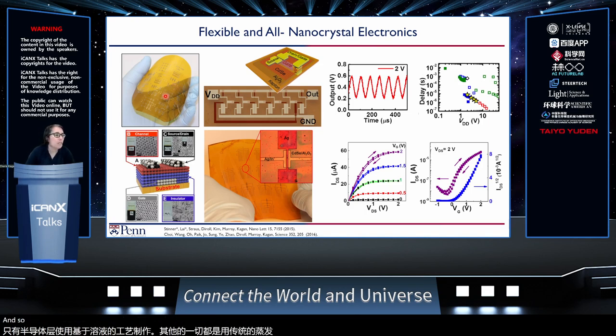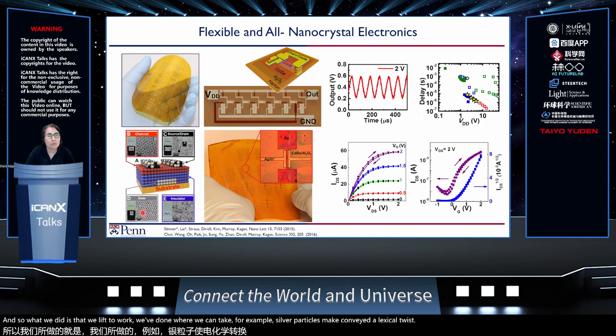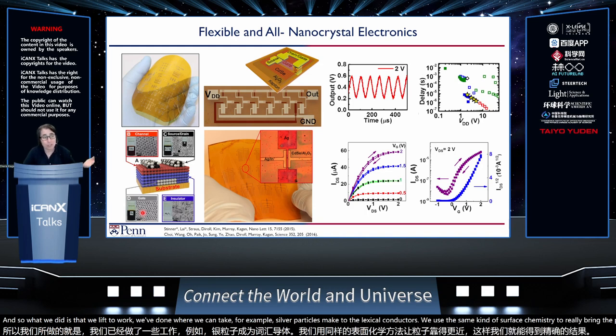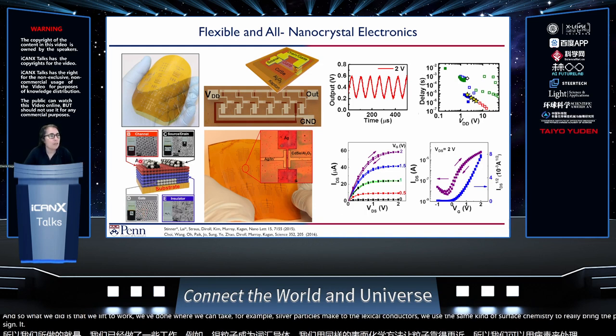So what we did is look to work we've done where we could take, for example, silver particles to make good electrical conductors. We use the same kind of surface chemistry to bring the particles closer together. Again, they are treated with thiocyanate. We use cadmium selenide to make the thin film.